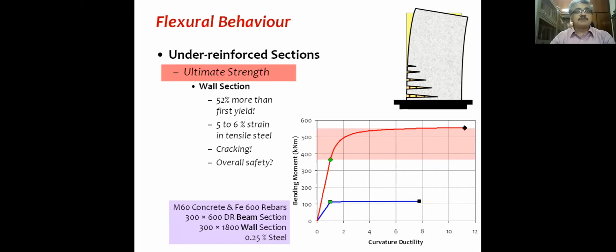What is the problem with that? Because our reinforcing steel has much higher strain capacity, elongation capacity. The problem is with cracking. With very high strain in the steel, there will be significant cracking, and that will lead to lateral deformation, reduction in stiffness of the structure as a whole.